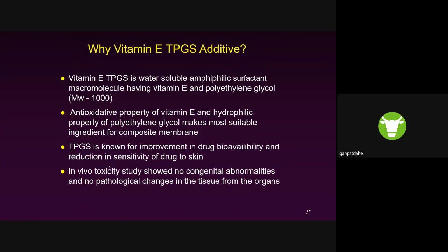Vitamin E TPGS is a water soluble, amphiphilic surfactant polymer. It has vitamin E and polyethylene glycol, and the vitamin E section acts as a head, and the polyethylene glycol section as a tail. This surfactant characteristic plays a good role in forming the skin of the membrane, which is called the selective layer of the membrane. In this case, the molecular weight of the polyethylene glycol was around 1,000 Dalton.